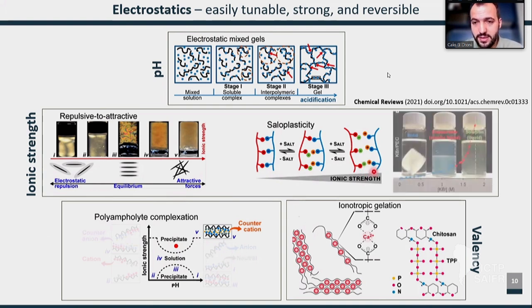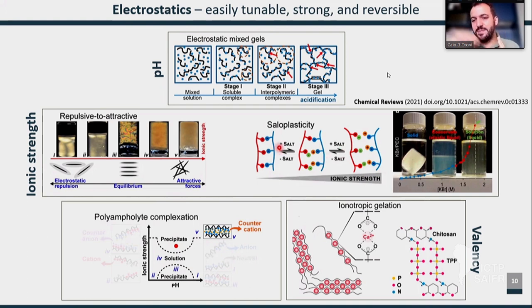And what is the implication of this? You can see here that you can go all the way from a solid-liquid phase separation in which, you know, the species complex completely and expel any water. So it's not hydrated, it's a real solid that is going to precipitate, to what we call the coacervation or the coacervate, which is a liquid-liquid phase separation. So there are two liquid phases, not a solid and a liquid anymore, two liquid phases, one in the bottom because of density, right? Rich in the polyelectrolyte complex, and one in the top, poor, but still containing the polyelectrolyte complex. And as you put more salt, you can reach a solution state. And it's reversible as you take out salt by dilution, by dialysis, by ion exchange. You really go the other way.